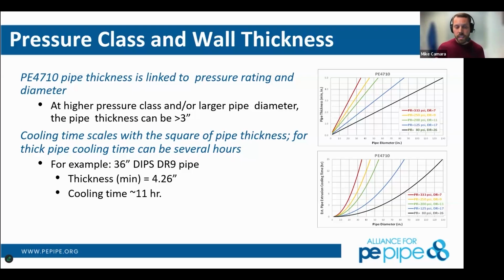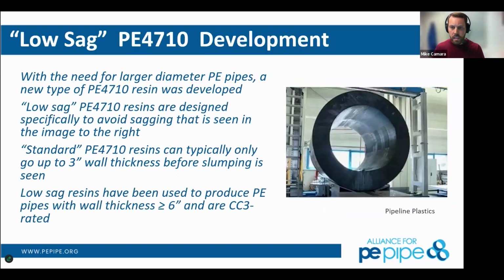That's substantial, right? And so all this time when you have this pipe in this molten state, gravity's pulling on it downwards, right? All this molten material is being pulled downwards. And so then what you get at the bottom is excessive material that's pulled there. And then you get this big deviation between your min and max wall thickness, which is an issue. You can be out of the standard. You could be wasting material, which is going to cost you money, right? And that's one of the areas in which we've tried to further engineer these polymers to resist that sagging or slumping to the bottom of the pipe. You can go on to the next slide here.